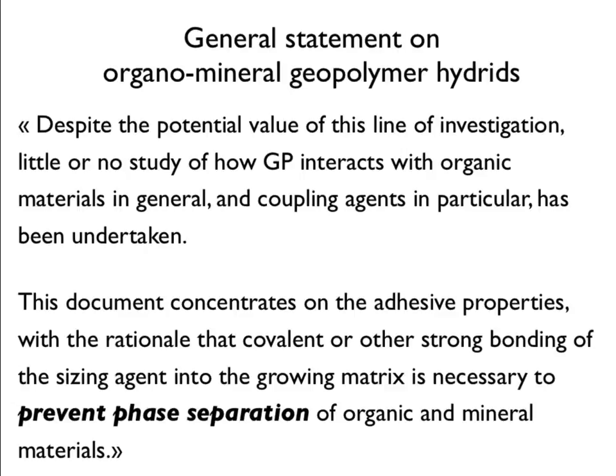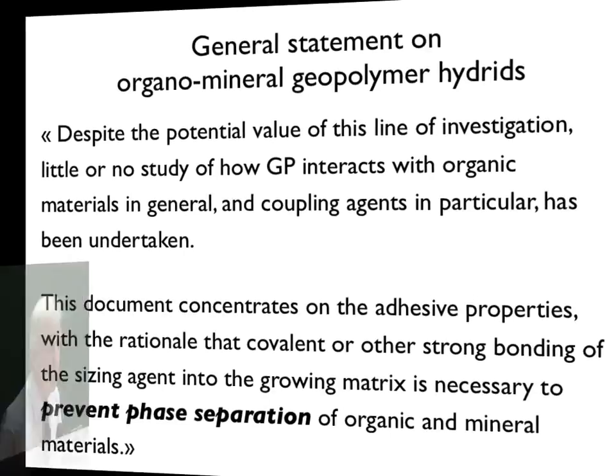This document concentrates on the adhesive properties with the rationale that covalent and other strong bonding of the sizing agent into the growing matrix is necessary to prevent phase separation of organic and mineral materials. Normally, an organic material is solvent-based and the geopolymer are not miscible. So something must be done in order to let them be miscible. Well, this is what they wrote.